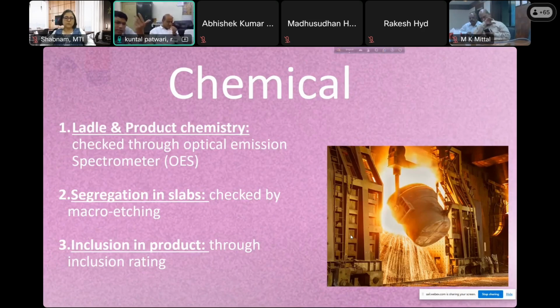Earlier, sulfur print was being done, but that practice has been stopped. That is not allowed. No one is doing it. It's very dangerous and hazardous. So we have moved on to macro etching. And finally, when the plate is rolled, this segregation line will try to change its position, and it might even collapse. It might even scatter. So in the product stage also, we do an inclusion rating, thick and thin series of oxide, sulfide, aluminate, silicates, and we try to assess how much inclusion content is present in the steel.